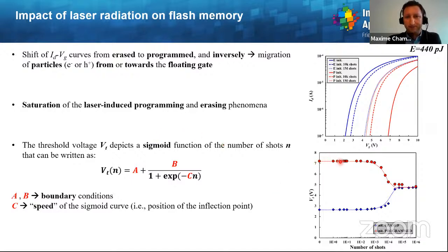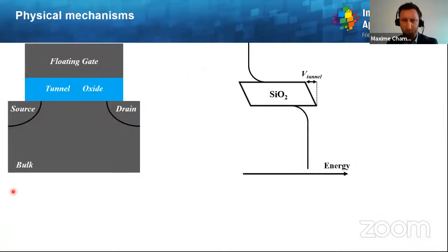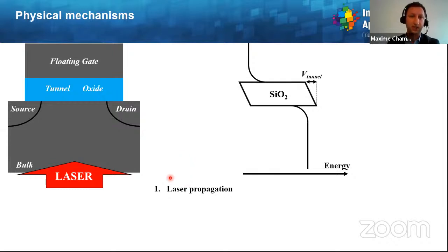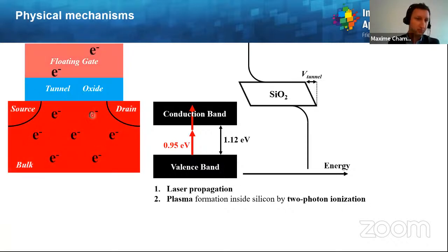Interestingly, the curve describing the laser-induced programming and erasing follows a sigmoid function of the number of shots. That can be written like this, where A, B, and C are three free parameters. A and B are related to the boundary conditions, and C is the speed of the sigmoid curve. So the whole game here will be to determine what A, B, and C are. But first, how can we explain physically this kind of laser-induced programming? Let us consider the device and the associated band diagram. The first mechanism occurring is the laser propagation, of course, which leads to the formation of a plasma in the silicon part by two-photon ionization.